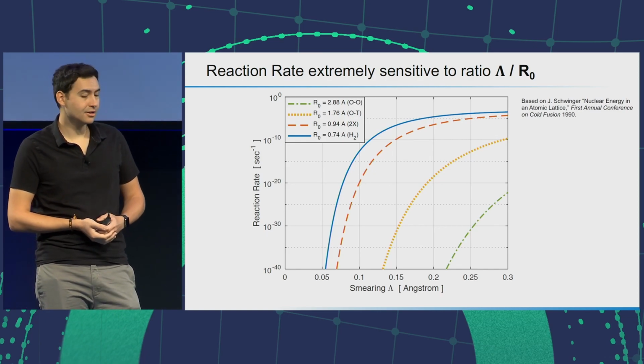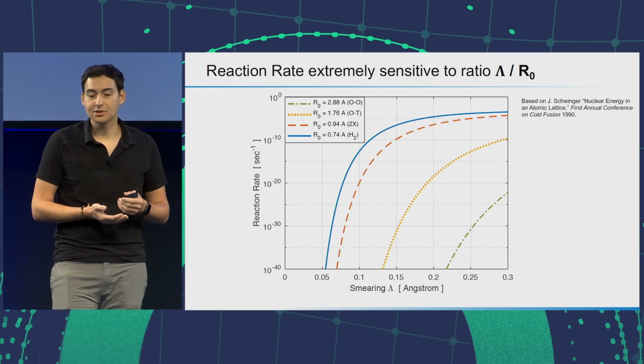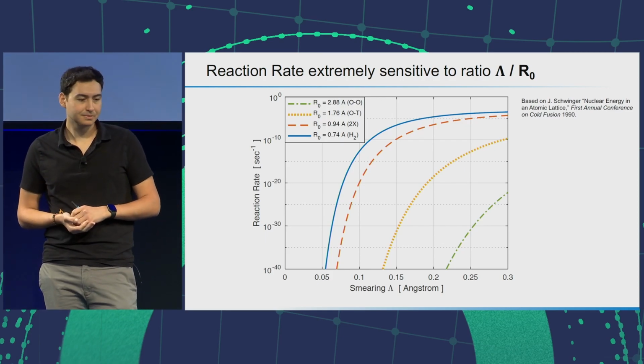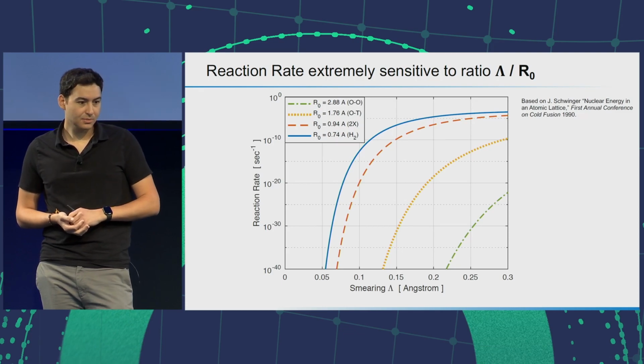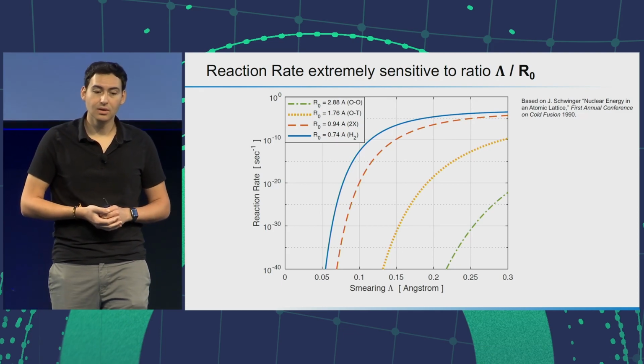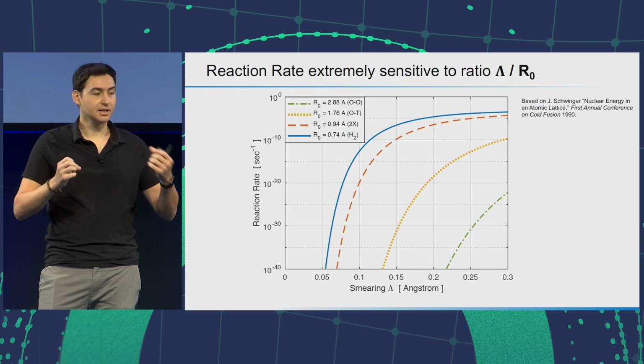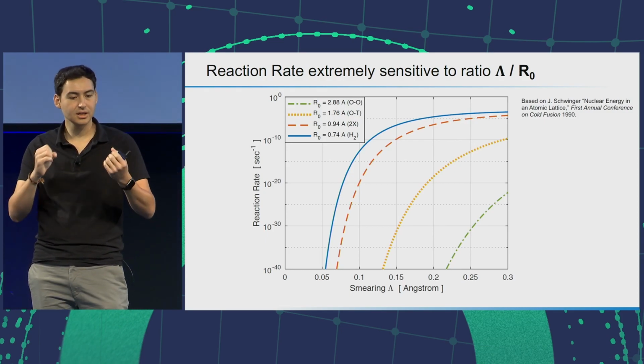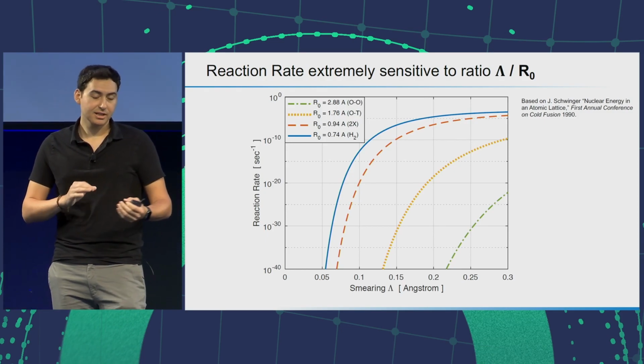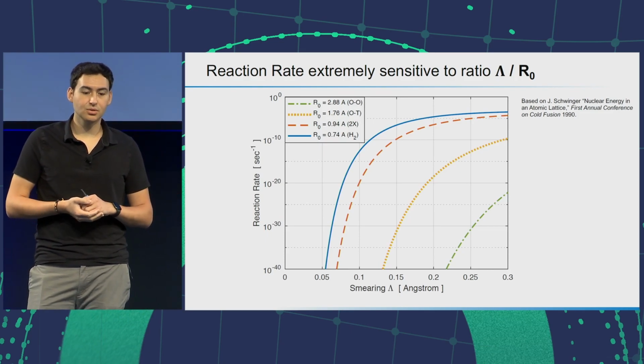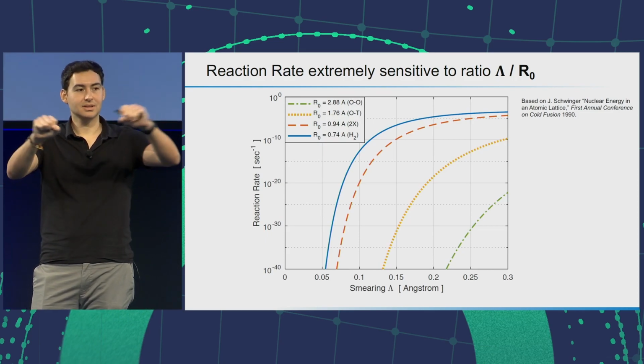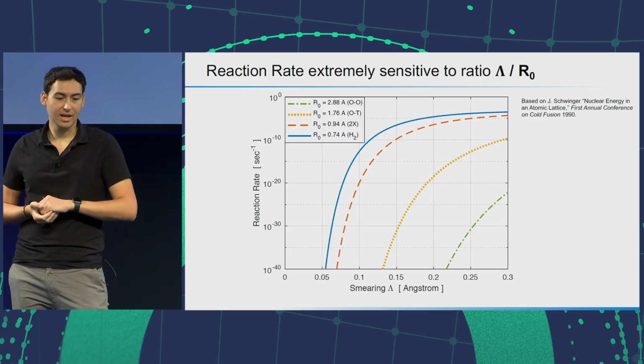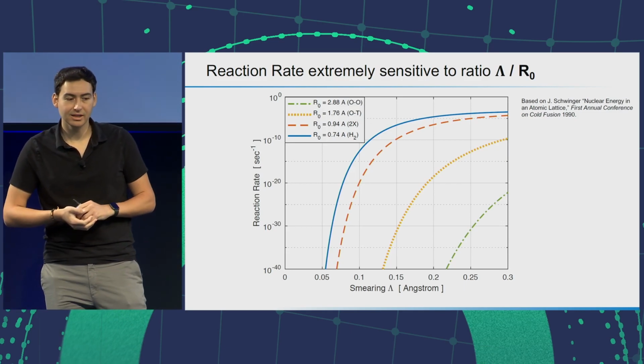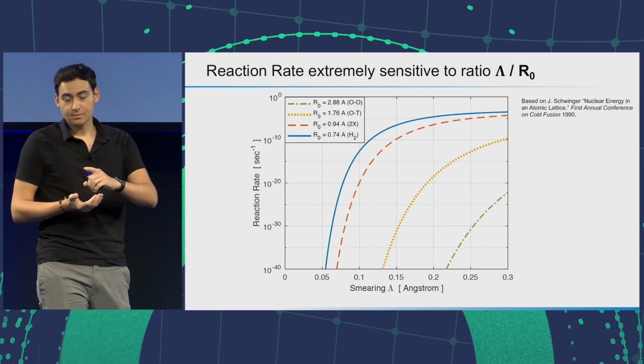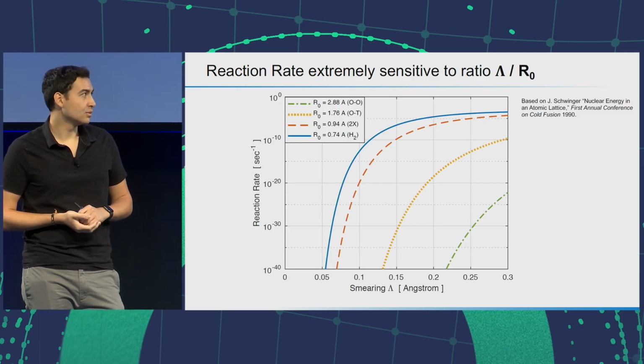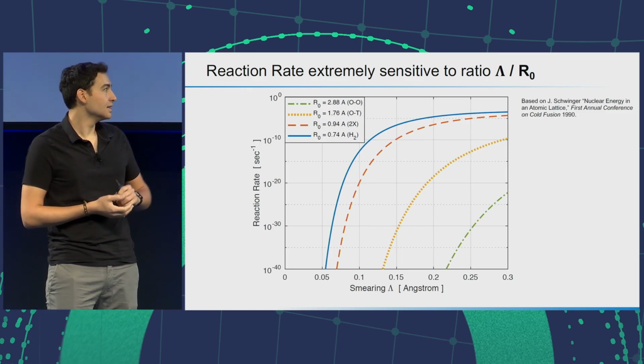And so what we're plotting here is the reaction rate in inverse seconds as a function of this smearing lambda in angstroms. The different colors represent different values of R0. So the green would be filling up octahedral sites. So that's the separation between 2 octahedral sites. The yellow is an octahedral tetrahedral separation, and the red is 2 deuterium atoms hopping into the same octahedral well. So a very high energy configuration, not an equilibrium configuration. And then the blue line represents what we can think of as an upper limit. It would be the pure hydrogen molecule taken outside of the lattice.